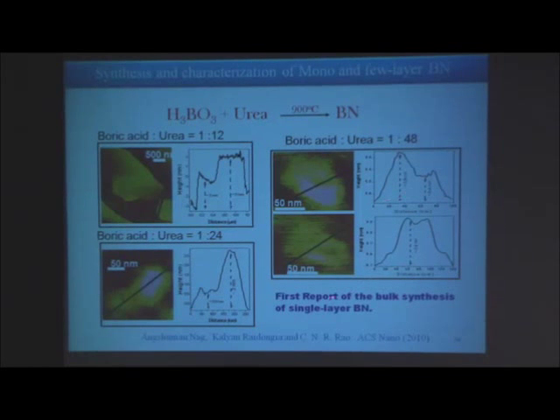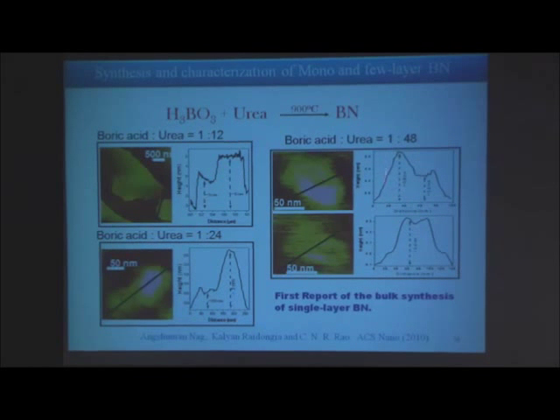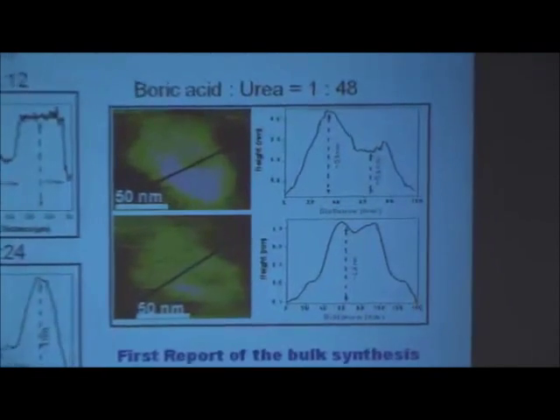Well, the same thing, why not graphene, right? Why not inorganic graphene? That is what I told myself. One sheet, why only carbon? Why not boron nitride? Why not molybdenum sulfide? So one of the best simple ways we did a few months ago, it has just come in ACS Nano, is take urea and boric acid, heat it at different temperatures. We have been able to make, you can see the AFM height, that height is exactly 0.3 nanometers, 1 layer of boron nitride.